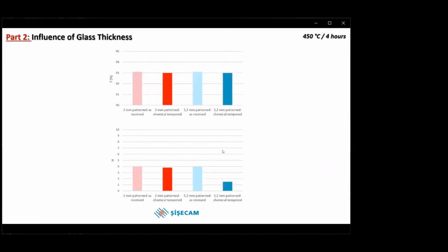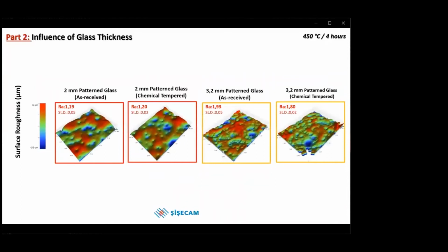When the optical transmittance and haze values of the samples before and after chemical tempering were examined, there was no significant difference in the transmittance values of the glass samples. When the haze values before and after chemical tempering are examined, while the haze values before chemical tempering were similar for both thicknesses, it was observed that there was a decrease in the haze values after chemical tempering. This decrease is greater in glass with a thickness of 3.2 millimeter. When we look at the surface roughness values, while surface roughness values don't change with the chemical tempering process, roughness values increase with the increasing glass thickness.